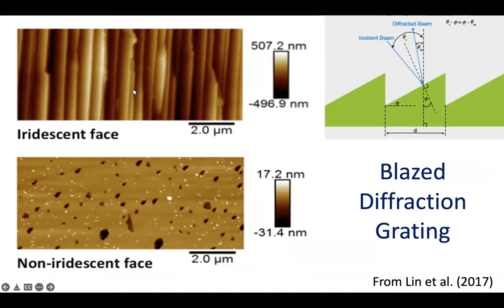We have this ridge and valley texture on the iridescent Z faces, but there's no iridescence on the R faces. And so this texture that we see right here is called a blazed diffraction grating. And the mathematics for this kind of constructive interference of the blazed diffraction grating is a little bit more complicated than just a thin film, but nevertheless, it's worked out. And still, there's kind of angle dependence to the color that is reinforced selectively. The distance on average between these blaze peaks was calculated by Sunny statistically, and she found it was something like 350 nanometers or so. Again, right in that sweet spot for visible light interference effects.